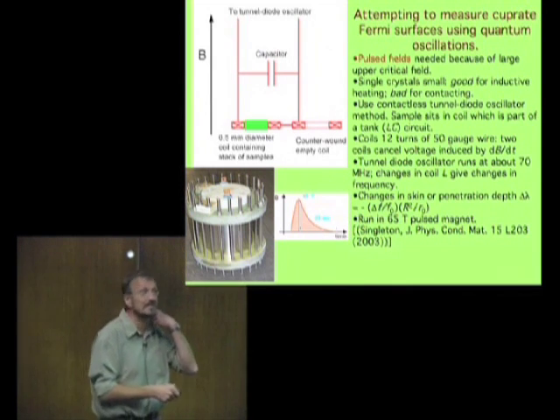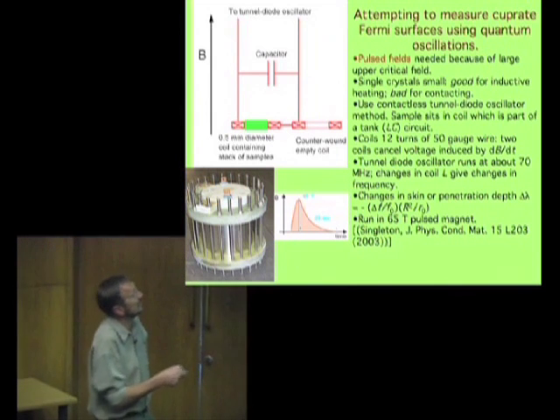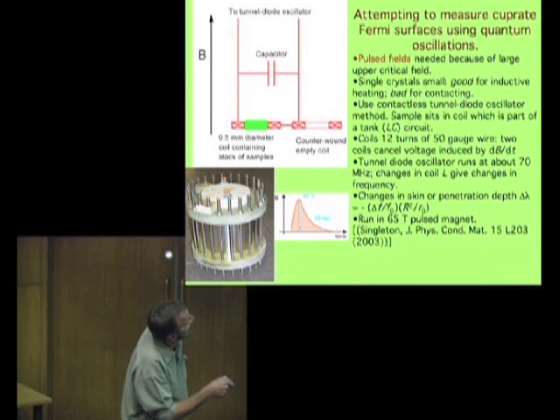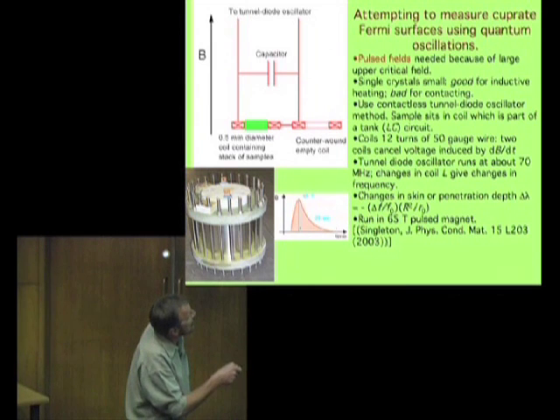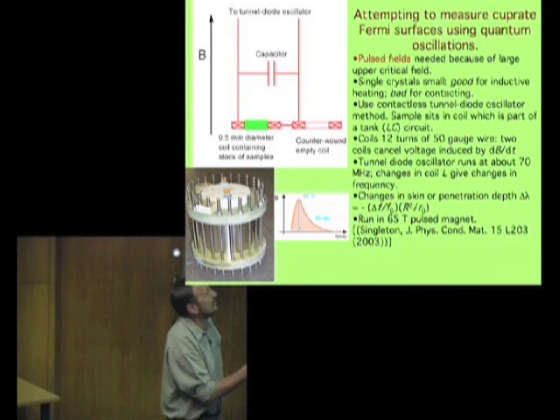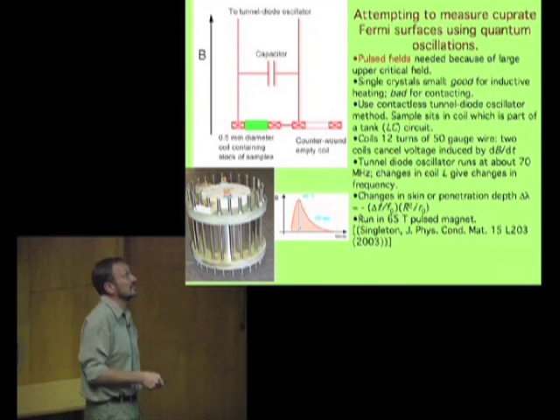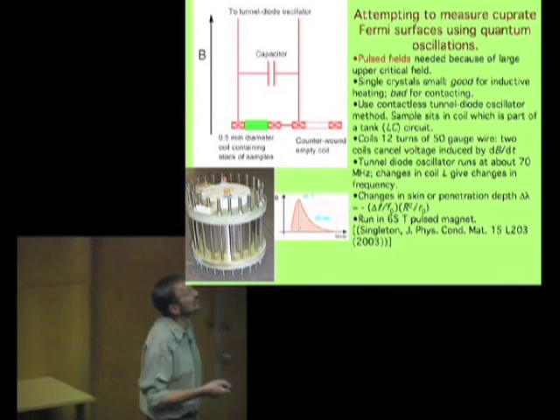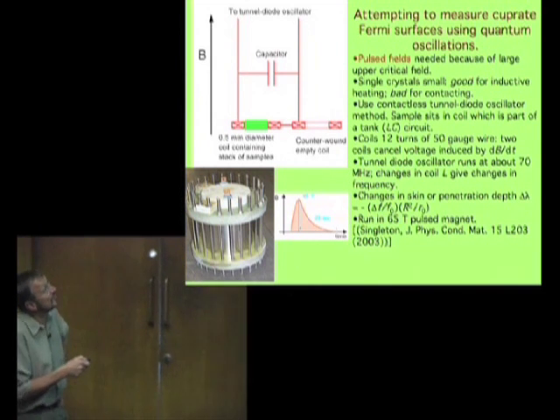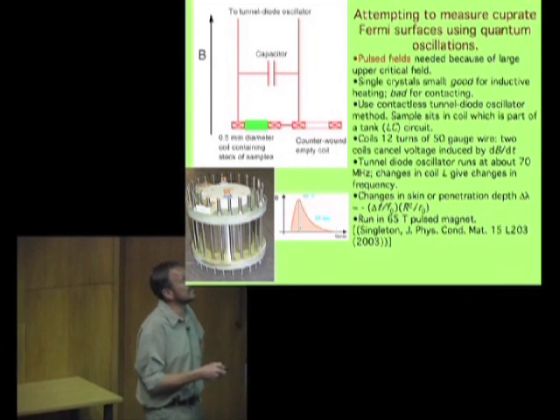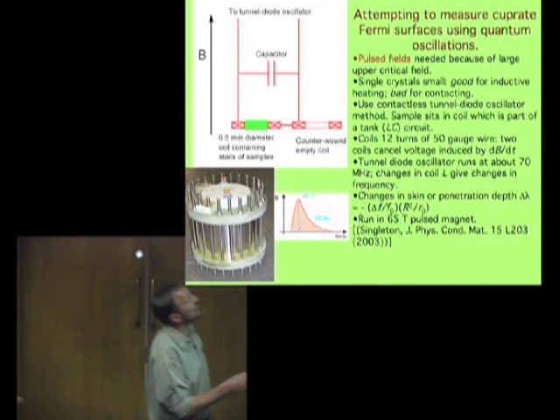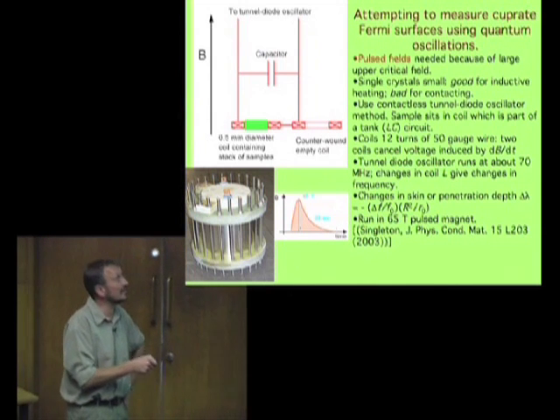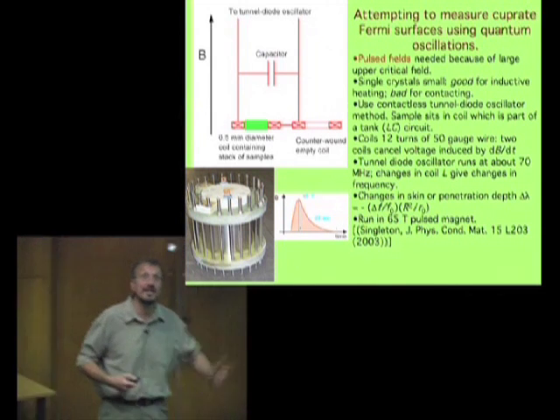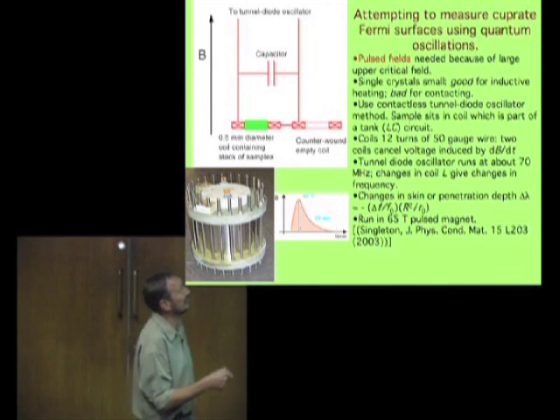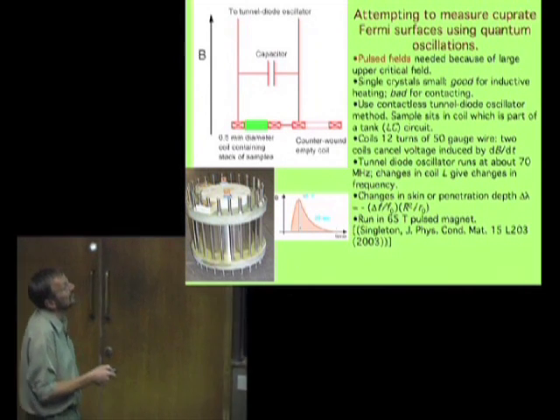The easiest way to get a high magnetic field is to use a pulsed field magnet, a thing like this here. This is a magnet that will give you a waveform in magnetic field versus time that looks like this. Peak field of about 65 Tesla, a duration of about 20 milliseconds. Now, the single crystals that we want to use for these experiments are small. This might sound like a disadvantage, but it's actually very good from the point of view of inductive heating. If you put a metal in a changing magnetic field like this, it will heat up because of eddy currents. That's a bad thing if we want to see these low temperature quantum phenomena.